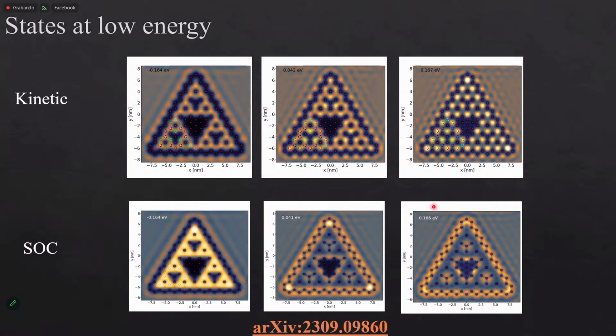And then as we increase the energy a bit more, we actually start to see states that sit in the edge. I'm going to show you in a few slides that this is quite close to what they see experimentally. So it's nice because, at least in terms of understanding the state that they saw, we can see it in the evolution of this method, just by introducing spin-orbit coupling at least.